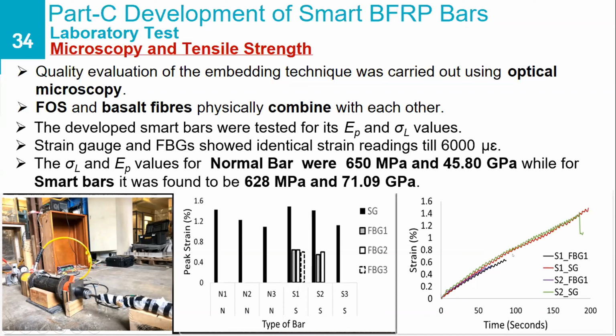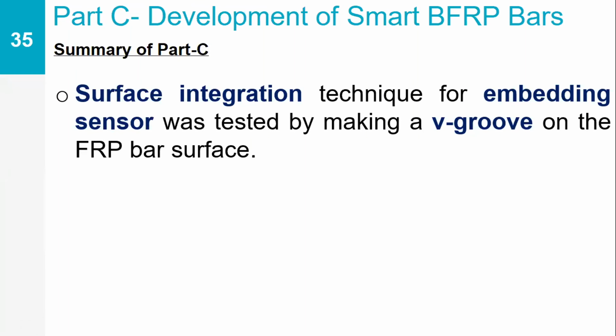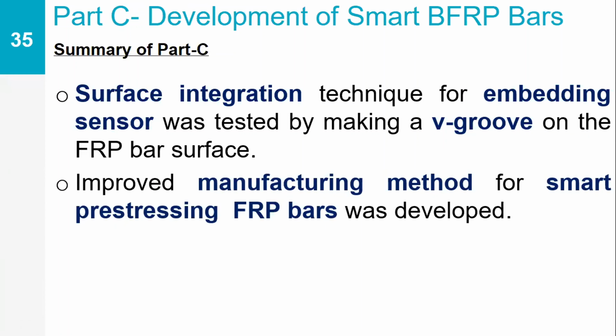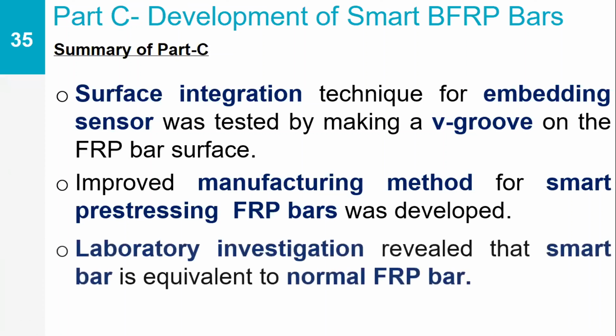If you use a different fiber optic sensor which can record higher strains, that can be used to record higher strains in these smart BFRP bars. And so basically the summary of this part is the surface integration technique for embedding sensors was tested by making a V groove, but it was found that there are chances of getting damaged at the anchors. And so an improved manufacturing technique for smart prestressing FRP bar has been developed, and the lab investigation revealed that these smart bars are equivalent to the normal FRP bars in terms of the fiber distribution and also in terms of the properties that have been tested.